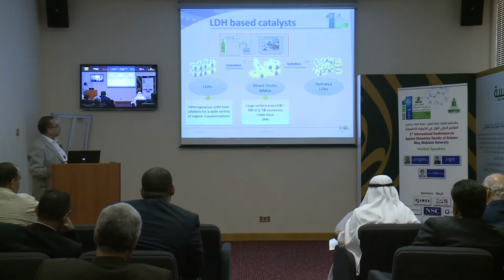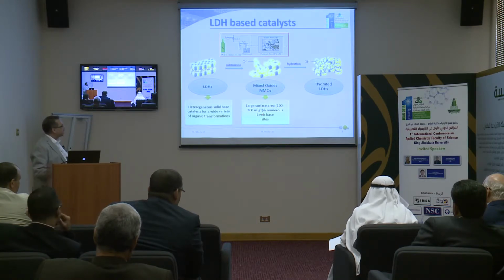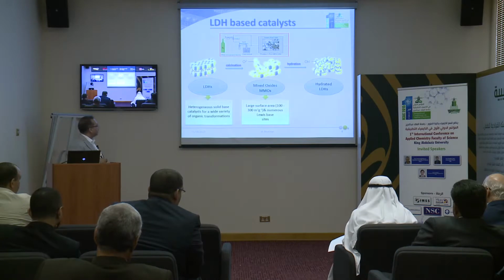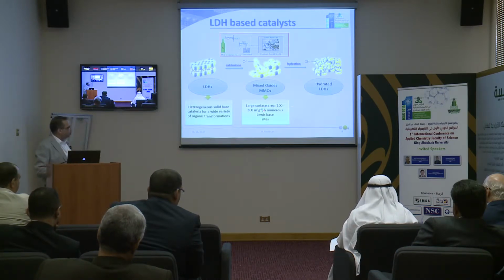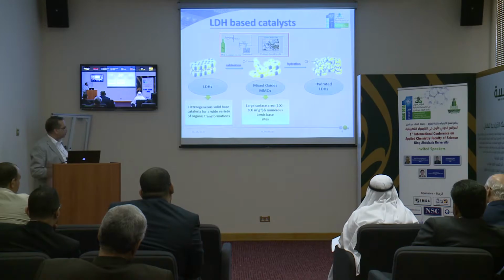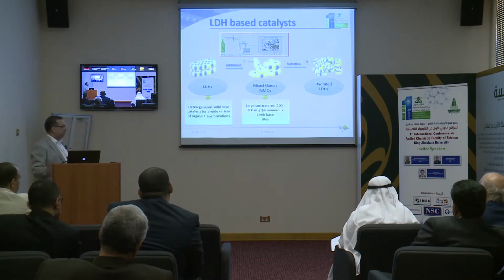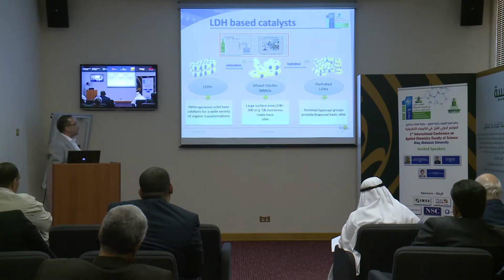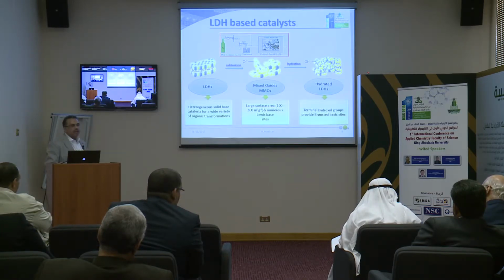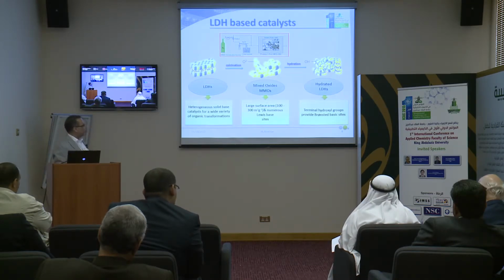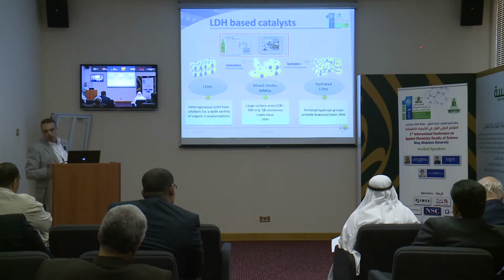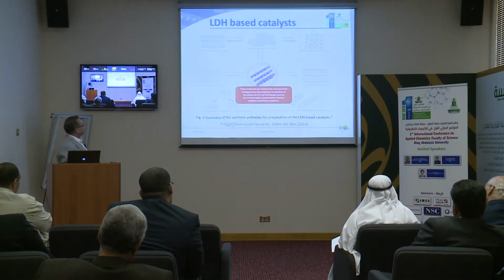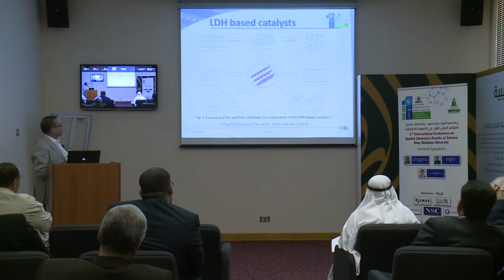And mixed metal oxides, because of the increased surface area due to the decomposition, removal of carbon dioxide and hydroxyl groups, we increase the surface area and porosity, as well as create Lewis base sites, so it will have other applications. Or rehydrate the material again by passing water vapor in the gas phase or liquid phase, so we could introduce other terminal hydroxyl groups which have another catalytic activity. So this is just a scheme to explain how many applications there are.